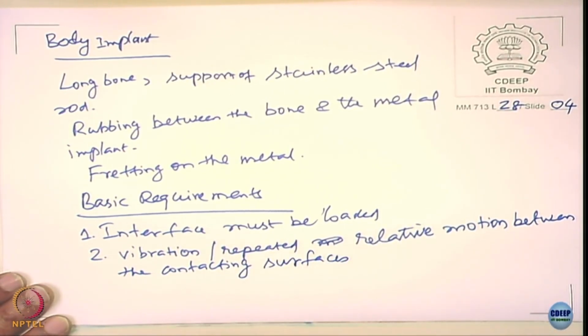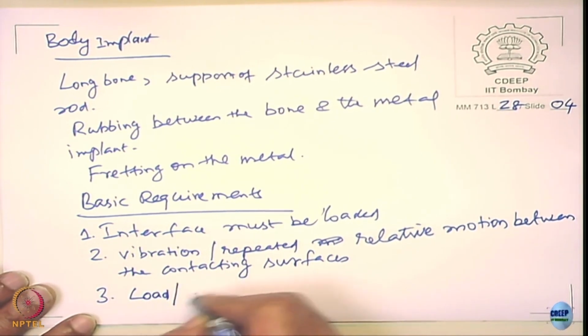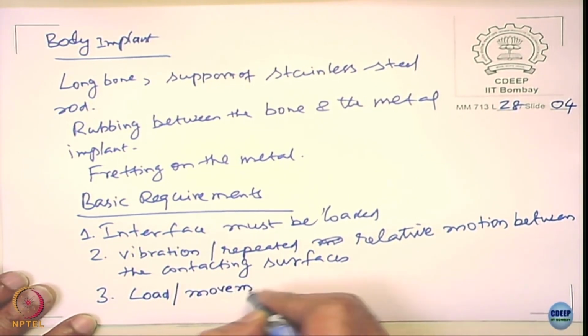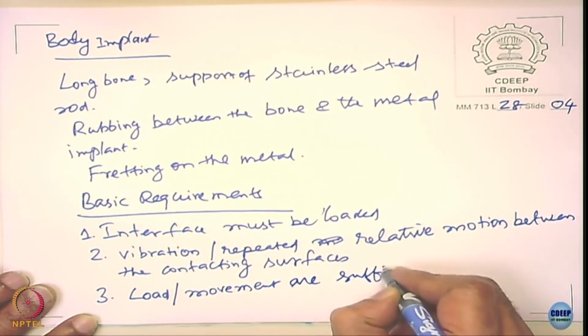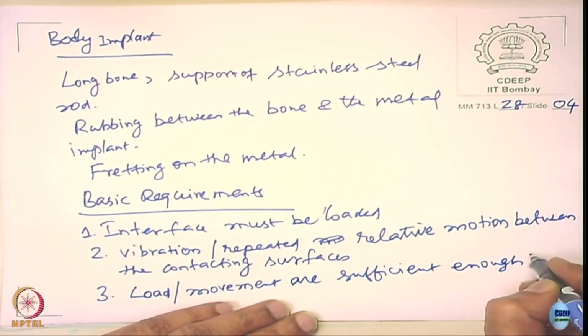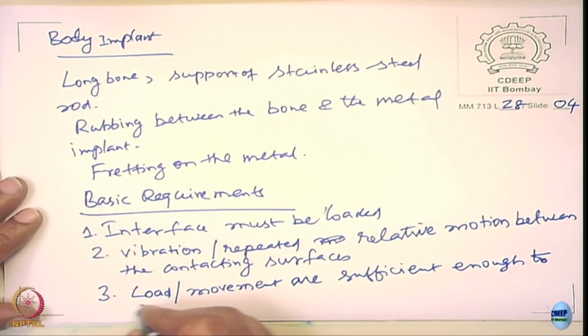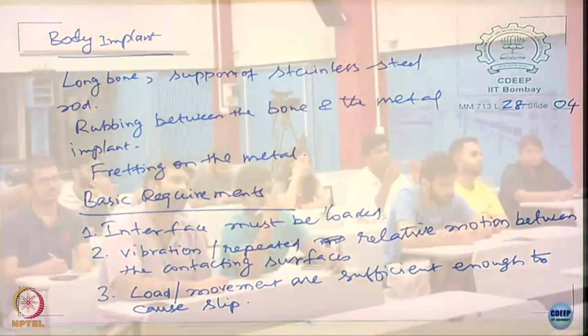Okay. Third, the load and the movement are sufficient enough to cause slip, right. So, it is a mechanical damage that is taking place.